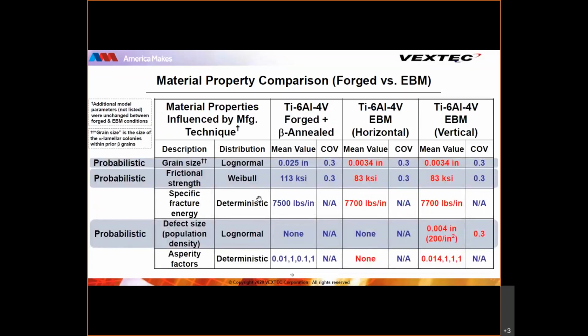microstructurally and looking at the differences, these 5 modeling parameters here: grain size, parameter frictional strength, specific fracture energy, defect size or presence of defects at all, and asperity factors. These 5 parameters were identified as being different between the forged condition, which you see in this column here, and the EBM condition, which you see represented by the vertical build and the horizontal build in these columns here. And the values in red from the EBM samples are measured values. So those are things that have been measured by researchers, and so we've accordingly taken those measurements and updated our simulation model with these values.